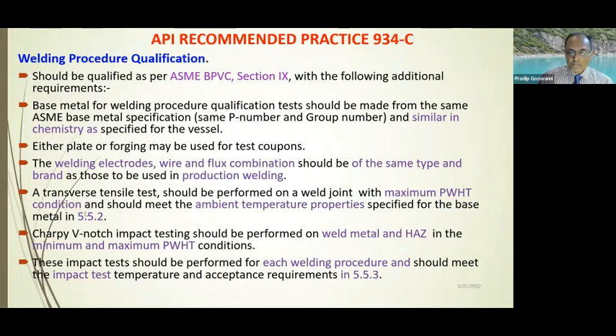And the transverse weld test should involve a maximum post-weld heat treatment condition and should meet the ambient temperature properties, that is impact temperatures also. A Charpy V-notch impact test should be performed on the weld metal and heat affected zone in the minimum and maximum post-weld heat treatment conditions. These impact tests should be performed after each weld procedure and should meet the impact test temperature and acceptance requirements as per this particular clause 5.5.3.